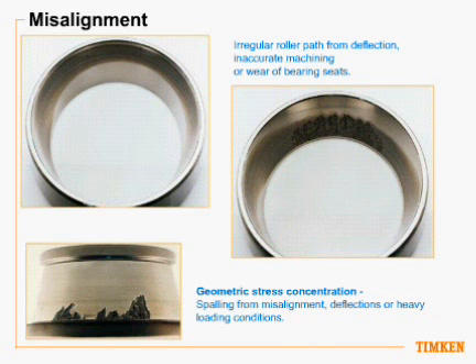Now, how about if you're installing a new assembly? Is it possible for that clearance to change and need to be reset after it's been run for a bit? I'm not going to say it's impossible, but if everything was set correctly to begin with, think about this: the only way you could gain more clearance in there, if you checked the assembly and let's just say you had 3 thousandths of end play, okay? Now let's say you come back, you're checking it again, and you know, 6 months, a year later after operation, you notice that there's 5 to maybe 10 thousandths of end play. The only way that is possible is either the cups weren't seated, so you never got the initial setting correctly, or there had to be wear somewhere.